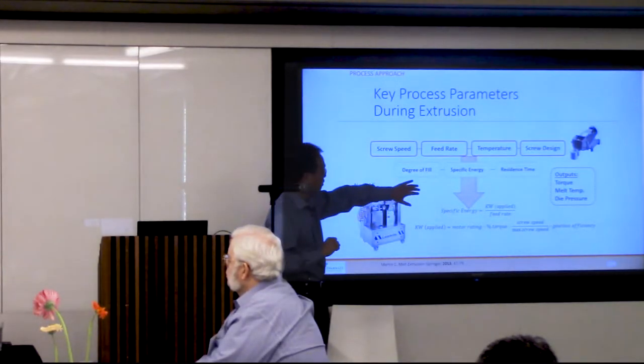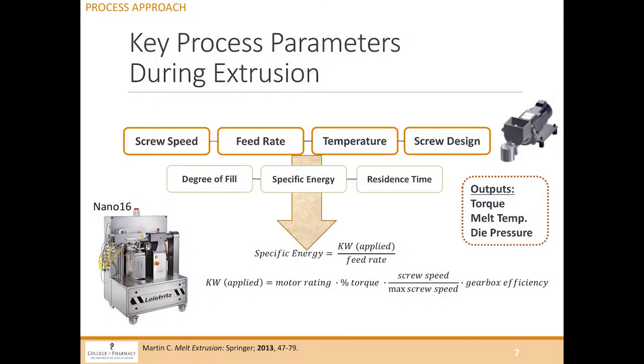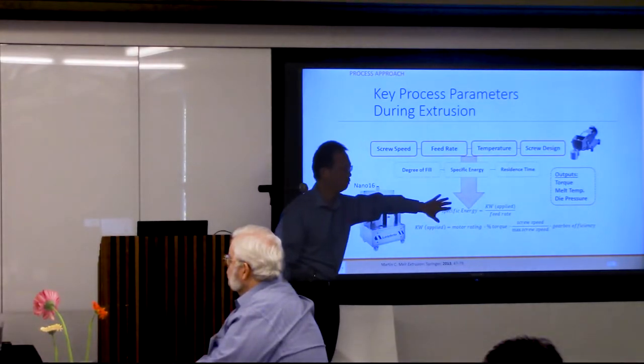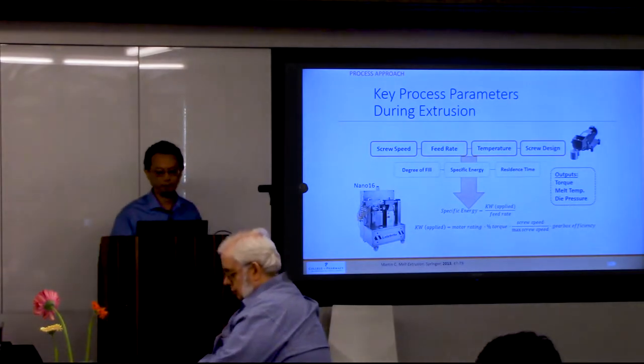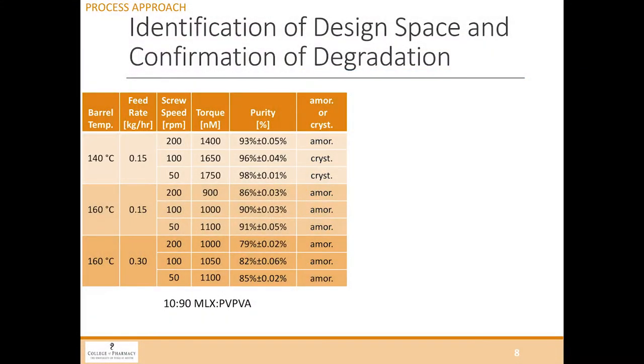At the end of the day, in the extrusion process, we rely on the screw speed with a certain screw design and barrel temperature. I think this is where a lot of drugs get prematurely killed, because in the small, early stage when you do small processes, the barrel temperature plays too much of a factor. But anyway, you use screw speed for the mixing, you use heating for the barrel, and you're trying to convert most of the energy you put in to help you dissolve the drug in the polymer. And you have to hit the minimum amount of energy. So early on, we did a small DOE, looking at different barrel temperatures, going from low to high. And within each barrel temperature, we varied different feed rates and also screw speeds. The larger the machine you go, the more important role the screw plays. The barrel actually is irrelevant.